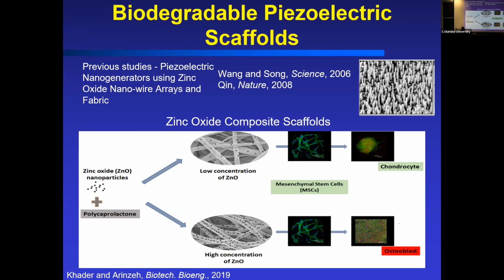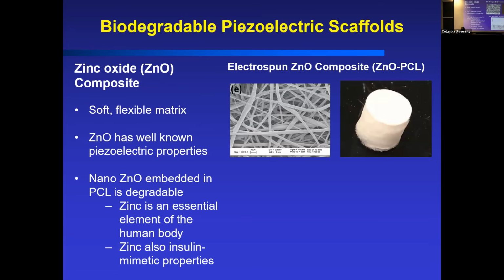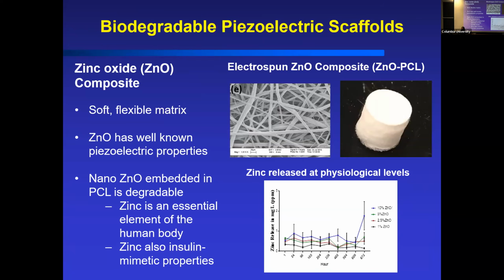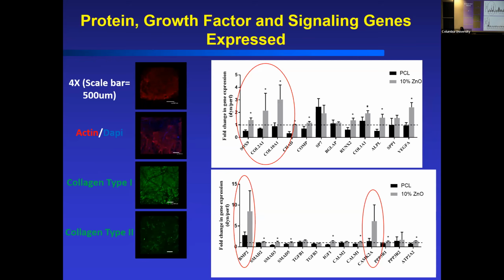We note that we can drive chondrogenesis. High concentrations of that zinc oxide in the fibers will drive more osteogenesis. And what's interesting about the zinc oxide is that it will degrade eventually. So the zinc oxide will release, you'll get ion dissolution of zinc out of these scaffolds. And zinc is nice because it is an essential element in the human body. So it does other things, right? And it's also been shown to be an insulin mimetic. So not only are you getting piezoelectric properties from this composite, but you're also getting this release of zinc, which can be beneficial in other ways.